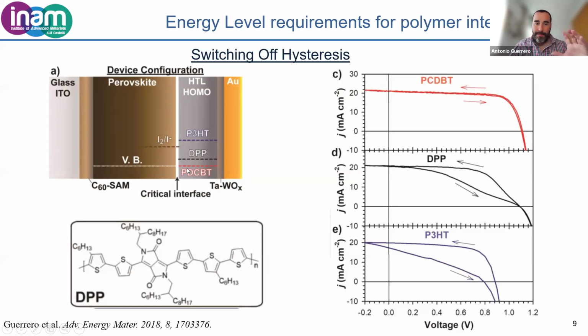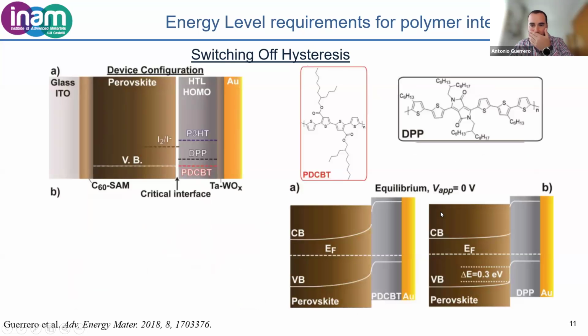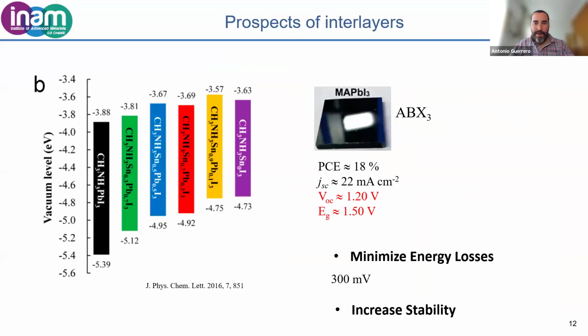The frontier energy levels of these polymers are very different, and the PDCBT is the one that is better aligned with the valence band of the perovskite. And the larger the difference between the HOMO level of the hole transport layer and the valence band of the perovskite, the larger the hysteresis we observe. Okay, so this work is from 2018, and we have progressed a lot over the last few years to understand the hysteresis, and this is what I'm going to explain in the second part of my talk.